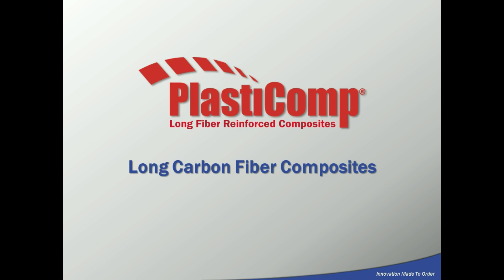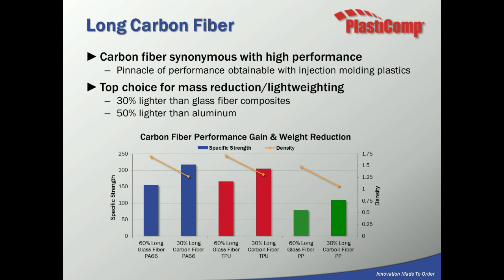So now let's switch gears and talk about long carbon fiber reinforced composites. Carbon fiber is synonymous with high performance. It's the pinnacle of performance in injection molded plastics. Carbon fiber is 30% lighter than glass composites and 50% lighter than aluminum. And the graph at the bottom is doing some comparisons where we're comparing long glass over on the far left. We'll look at 60% reinforced to 30% long carbon reinforced nylon 6/6. As you can see, even at the lower loadings, we have higher strength, and that also helps with the lower density to reduce weight.